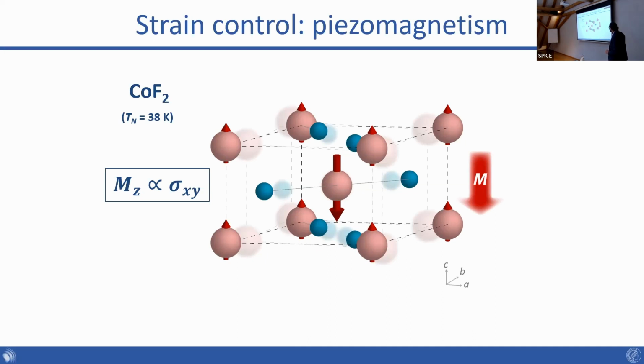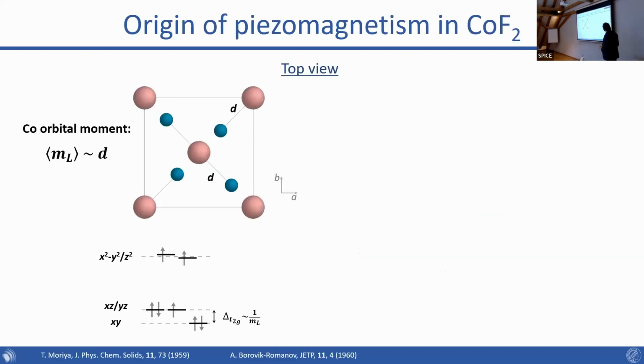And so, we want to understand how we can take advantage of this using phonons. So let's try to understand what is the origin of this piezomagnetic effect in cobalt fluoride. And that's easiest to understand from the top view. So now we're just projecting onto the ab plane. And what I think is the key to understand here is that we have a cobalt in the d7 electronic configuration, and the orbital moment here is not quenched. Okay, and that's key because the orbital moment is essentially going to be related to how split the t2g levels of the cobalt are, which is related very closely to the crystal field and to the bond lengths in this material.